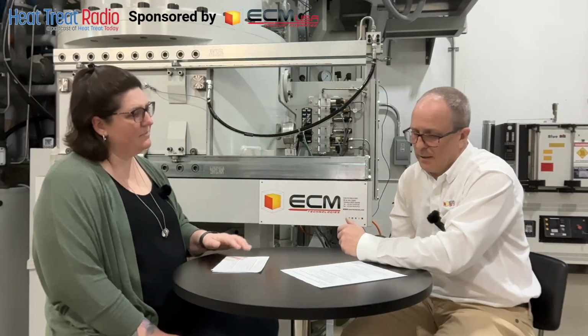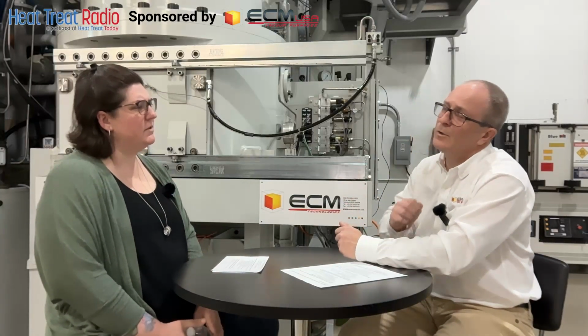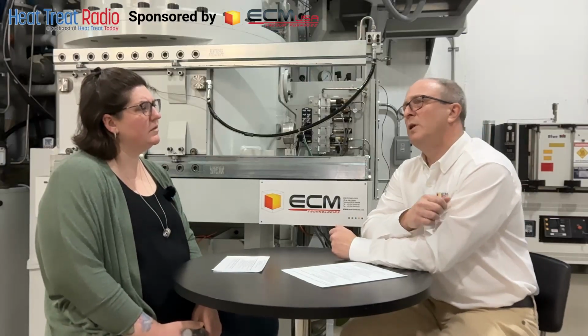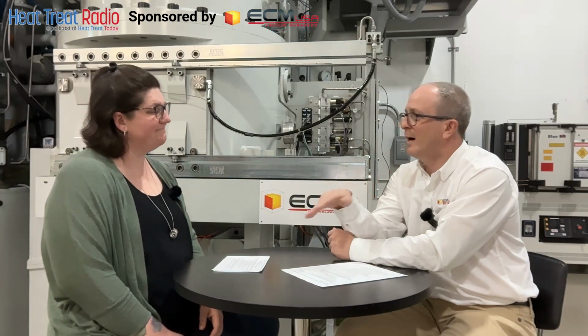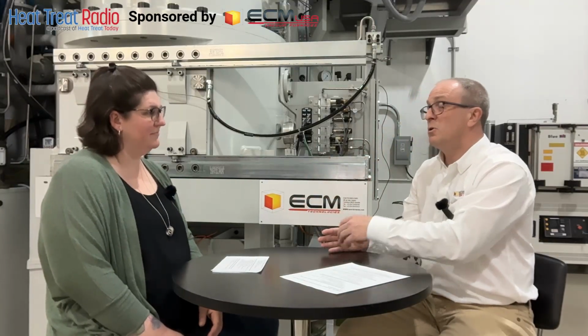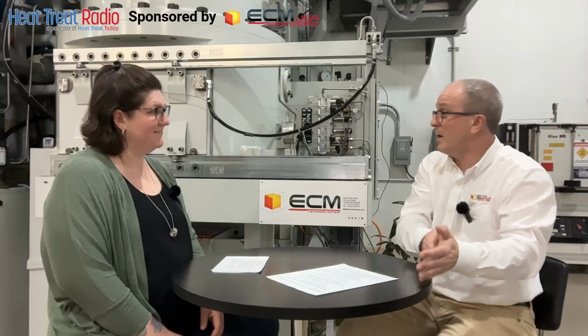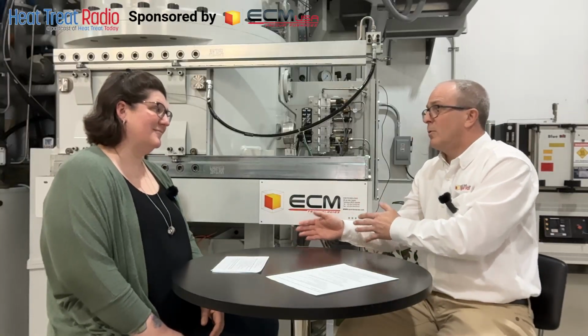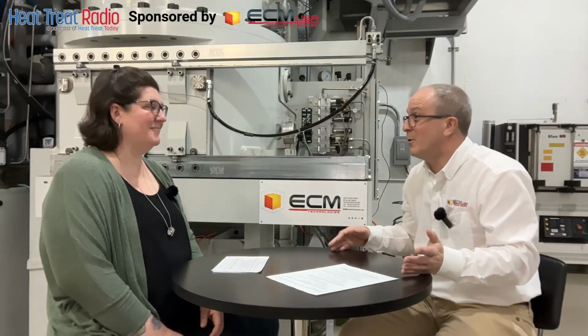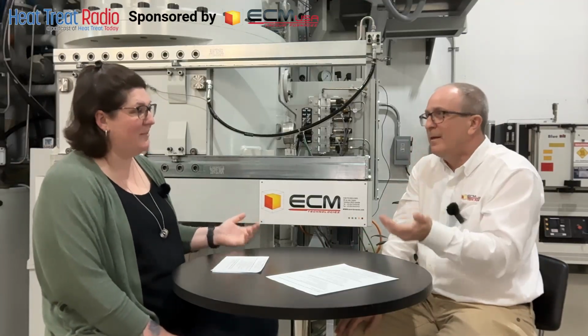How about the quench media? So the quench media, when you develop a recipe, if you do a quench, you will always do austenitizing. Classic, you don't want a crack, and you will do your carburizing, austenitizing, and go to oil quench. So it's pretty easy to switch from atmosphere oil quench and vacuum oil quench, because technically the recipe is pretty much the same. And we're going to cover that ground extensively, because I know it's kind of scary to even consider that possibility.